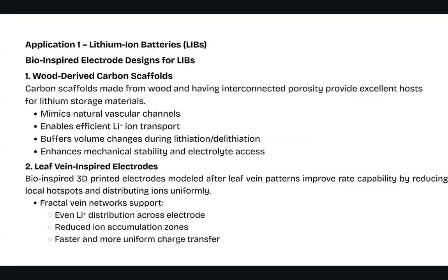So this is the first application, which is lithium-ion batteries, or LIBs. Bio-inspired electrode designs for lithium-ion batteries. First we have wood-derived carbon scaffolds. The carbon scaffolds are made from wood and they have interconnected porosity, which provides excellent host for lithium storage materials. So there are a few points. It mimics the natural vascular channels. It enables efficient lithium-ion transport, and it buffers volume changes during lithiation and delithiation, and it enhances the mechanical stability and also the electrolyte access.